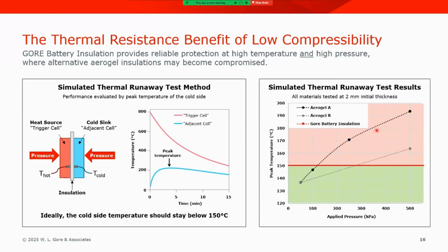Compare that to the aerogel B material. Again, we're starting out fairly low under modest pressure, but once we get to 500 kilopascals, now we're well above 150, almost 165 degrees C. So now let's compare this to the performance of GORE battery insulation.